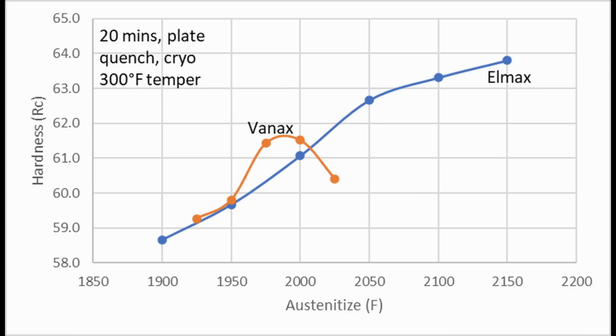So usually it's better to go a little bit lower temperature. So we would use something like 1975 rather than 2000, maybe even a little bit lower. Because even at the peak hardness, sometimes we are creeping up into the regime where we have more retained austenite than we would prefer.